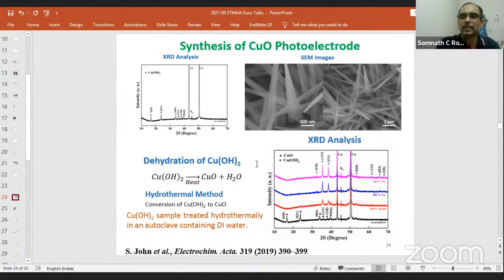Whatever we looked up in the literature, and when we try to do that, unless you are very, very careful, you can get this nice single needle type nanostructure. But if you are not careful, you will always land up with a mixed phase of CuO and Cu2O, cupric oxide and cuprous oxide. Why? Because the oxidation is not complete, and then you have an insufficient oxidation somewhere in these growing structures, which results in a mixed phase.